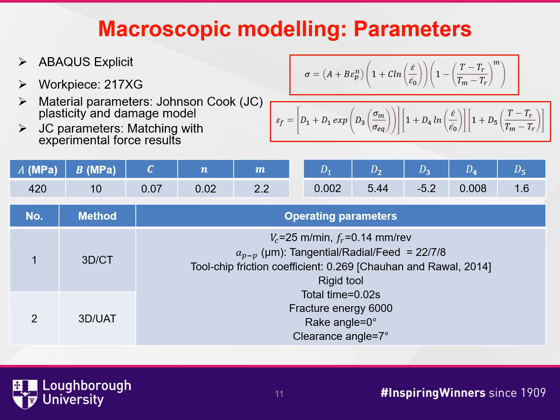Simulations of the conventional and ultrasonic turning processes were performed. Johnson-Cook plasticity and damage model was used for macroscopic material parameters for the MMC. The equations of the plasticity and damage model are shown in the red boxes. The JC parameters were optimized with the experimental CT cutting force result using PCD tool. The same cutting conditions were applied to the model with the experimental parameters.